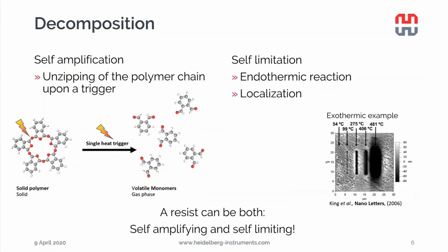Then in the decomposition, we have two effects that at first look might seem like opposites of each other, the self-amplification and the self-limitation. They are, however, not opposing effects, but two different things that can both happen in a single resist. The self-amplification means that we can unzip a whole polymer chain upon a single heat trigger. In this example, if we break with the heat trigger this carbon-oxygen bond and the polymer is self-amplifying, then this unzipping reaction spreads across the whole polymer chain, and we're left with 5 volatile monomers.